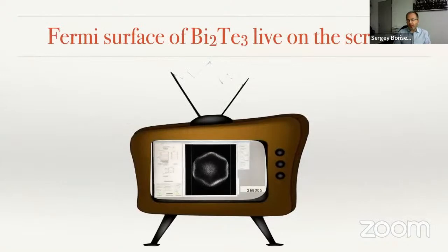This is the promised view of the Fermi surface live on the screen. This is a real-time video, and the bismuth telluride can be watched directly. This is the more or less stable situation, stable on the scale of hours, but you can track the development of this Fermi surface on the scale of basically seconds.